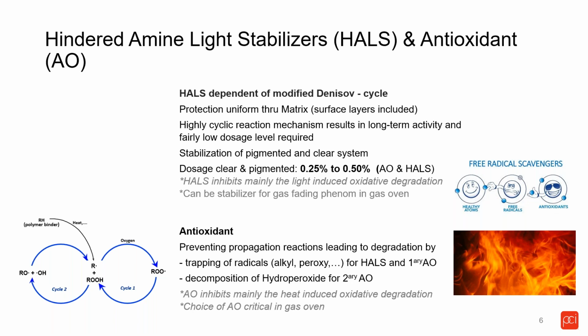So to summarize, two types of antioxidants, the primary antioxidant and the secondary antioxidant. Why are they needed in my powder coatings formulation? Primarily because you are extruding your powder coatings, or extrusion of the powder coatings is part of the formulation of it, which means we have a great deal of heat, and we need to protect the coatings from that heat during the oxidation process. But also the baking is done at a quite high temperature, and we also need an antioxidant for those two phases, if you want, of the heat cycle of a powder coating. The preparation, the extrusion, needs an antioxidant, and then the baking, which is done at high temperature, will also need an antioxidant. So to summarize, for heat stability, we will use an antioxidant, primary or secondary.